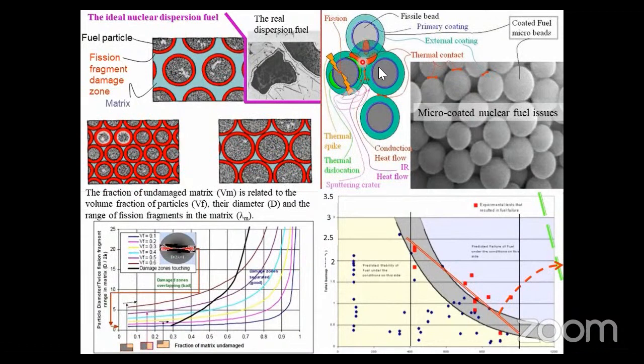Here is a pebble bed reactor-like fuel, but at a micro level, a few microns, coated in graphite, but it has issues about heating, and here is how it looks. But this is a dispersion theory, which appeared in the 1950s, and they observed that the smaller the fuel is made, the better it is for fission product damage. And here is what we are aiming at with a new product.